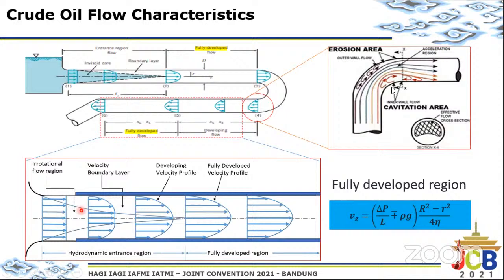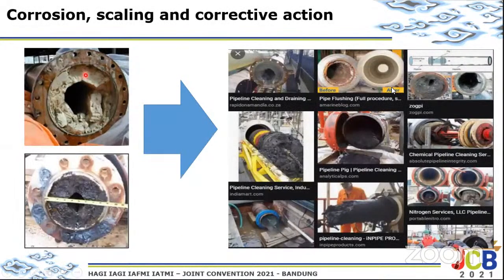This is if we know about the development characteristic of flow. We see in the center of the pipeline or piping, the velocity is optimum. And near the surface of the pipeline, the velocity is near zero, as the formula by the fully developed region. This is the characteristic and formulation, but in the visualization, the velocity at the center is higher than at the surface of the pipeline or piping system. Actually, with that condition, the scaling tendency may have higher potential at the surface of the pipeline rather than at the center, or centroid, of the pipeline internal.